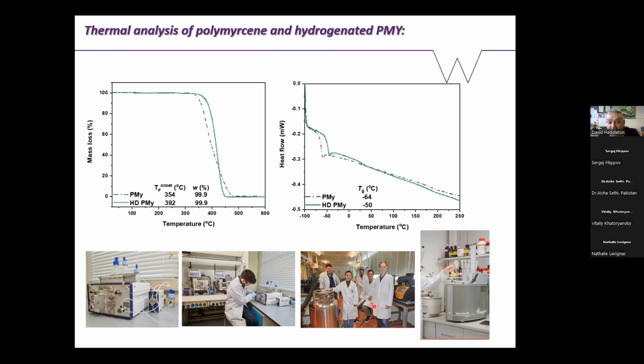And by hydrogenating it out, we change the Tg and we change the thermal stability. Again, this product is designed for an automotive lubricant. So it has to perform above 300 degrees centigrade. We don't want oxidation, and we want no reactivity or cross-linking. Really. So that's what I've got to tell you.